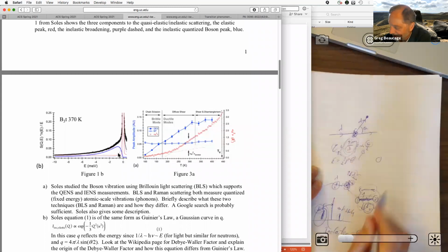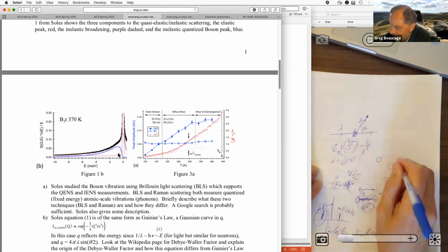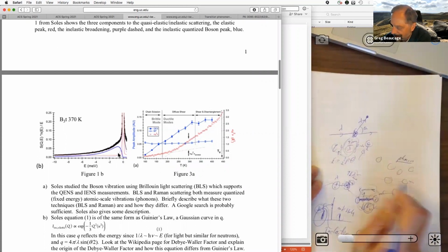If you're looking at a crystal, okay, so you have some kind of crystal, and then there are what are called lattice vibrations that happen. Right? And those can be longitudinal or transverse. In other words, it can be a compressive wave like a sound wave, or it can be a shear wave. So if you're looking at a lattice vibration, then you call that a phonon, right? So a phonon is like motion of atoms that is quantized because they're atomic size, so quantum mechanics governs it. So they're fixed energy. Because they're fixed energy, it's inelastic scattering, and the different kinds of phonons that you can talk about lead to different peaks in this, right?